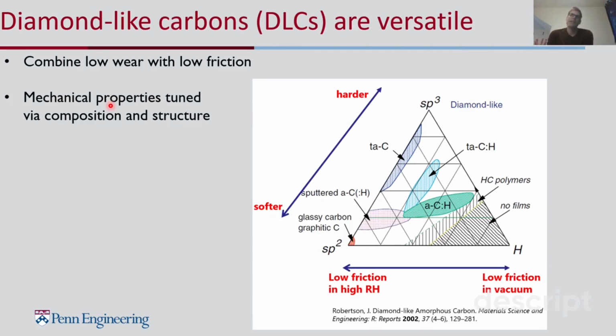Additionally, on the left axis here, we have the carbon hybridization ratio, and this can range in these materials from almost fully sp2, so it's a soft graphitic type material, all the way up to very highly sp3, where it's very diamond-like. And this basically controls the wear rate in these systems. And so the particular material I'll be talking about occupies the center of this diagram, and it's a variant of hydrogenated tetrahedral amorphous carbons, right around here.